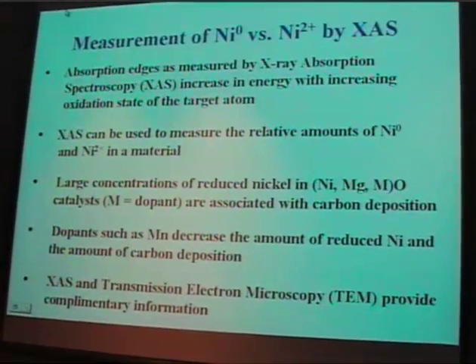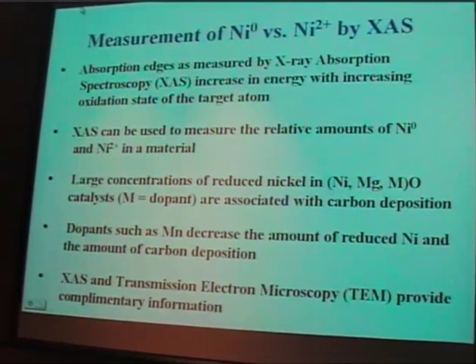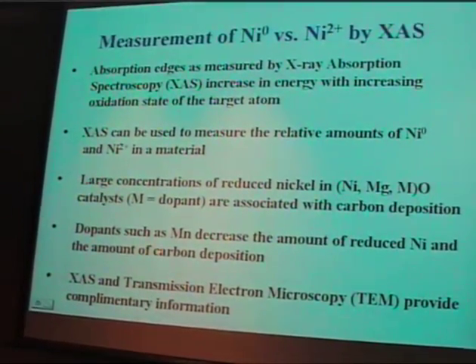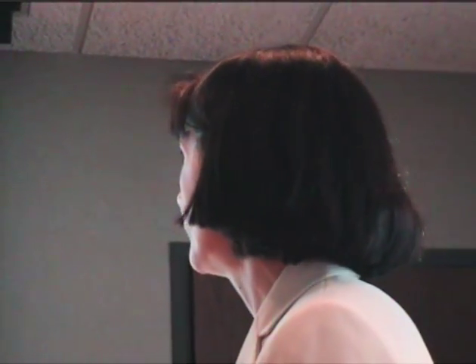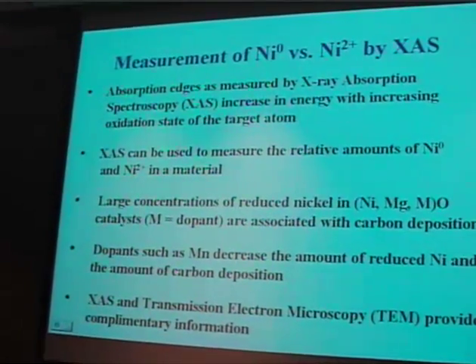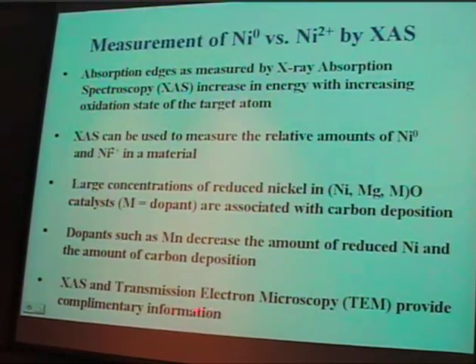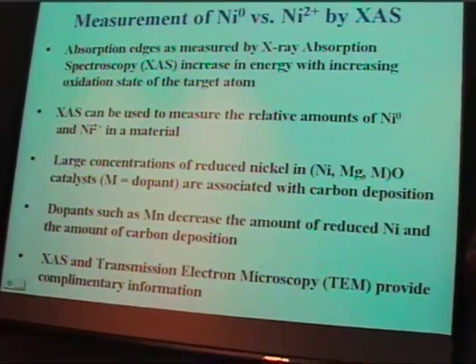So we had beam time. We had an opportunity to do X-ray absorption of the fresh and spent catalyst sets, and we were able to measure how much nickel 0 and nickel +2 is present by looking at the absorption edge. And that will tell you basically something about the oxidation state. And so that was very instructive. We were seeing large concentrations of reduced nickel when there wasn't any promoter, and that would be associated with the carbon deposition. With the manganese there, that's generally not the case. And so it was a nice confirmation with our TEM work, providing us with the same conclusion.